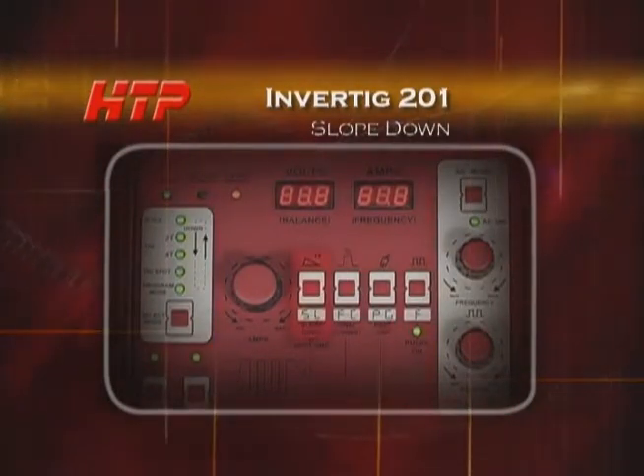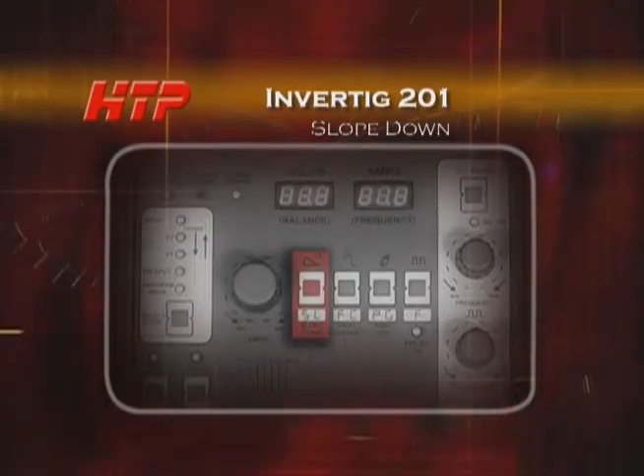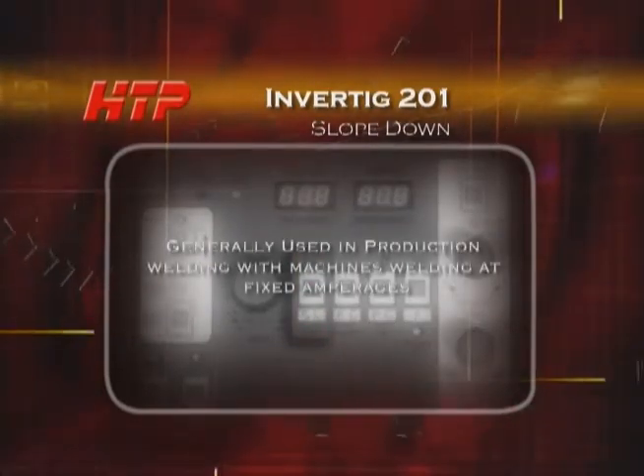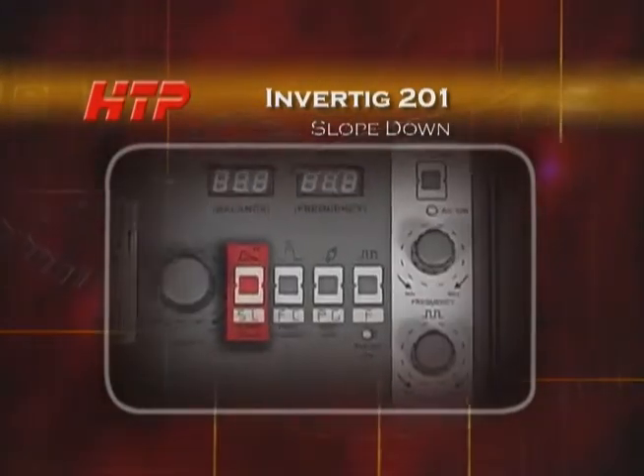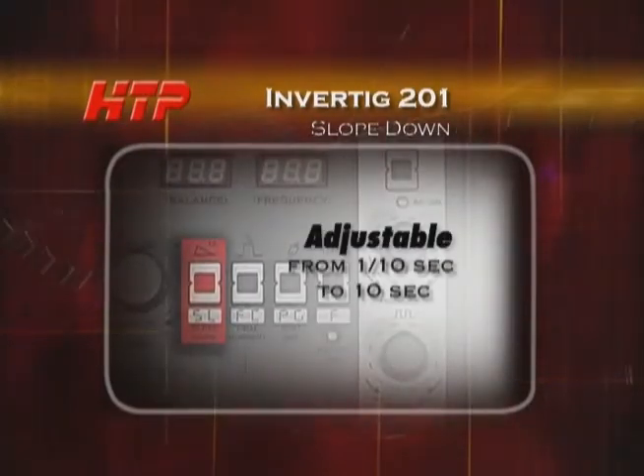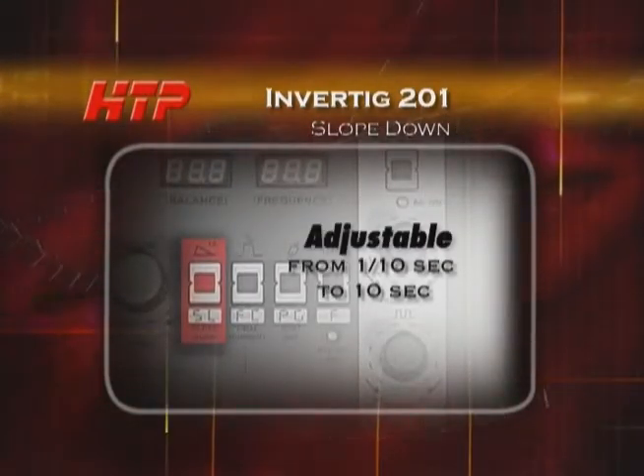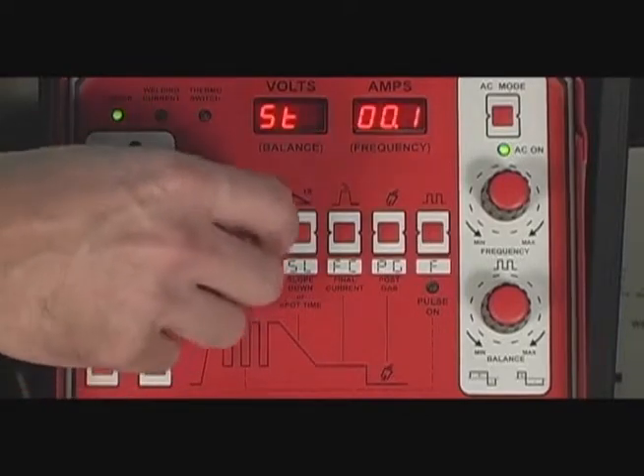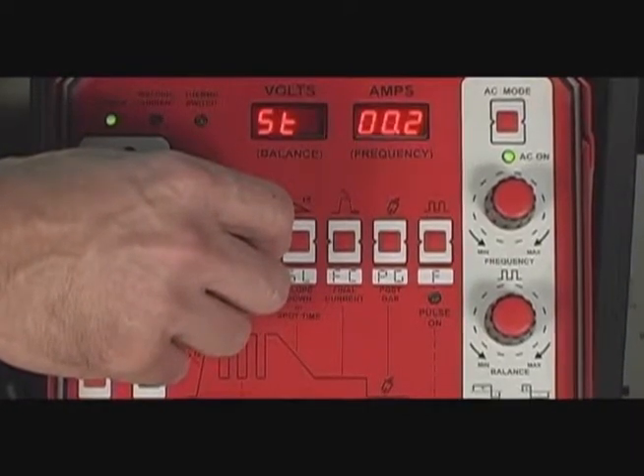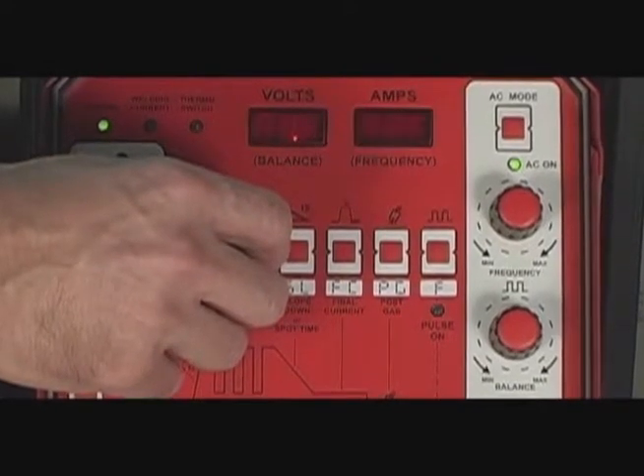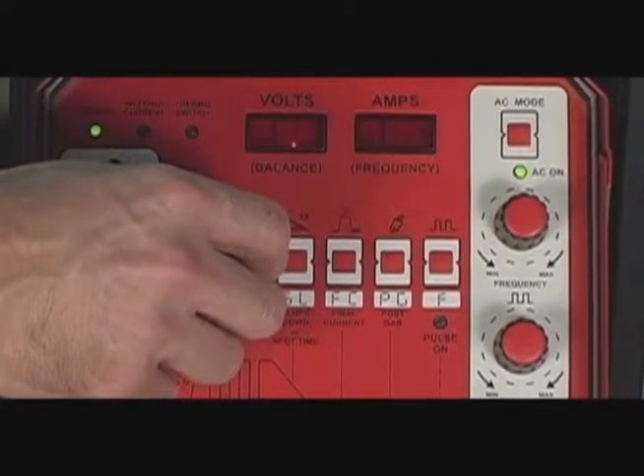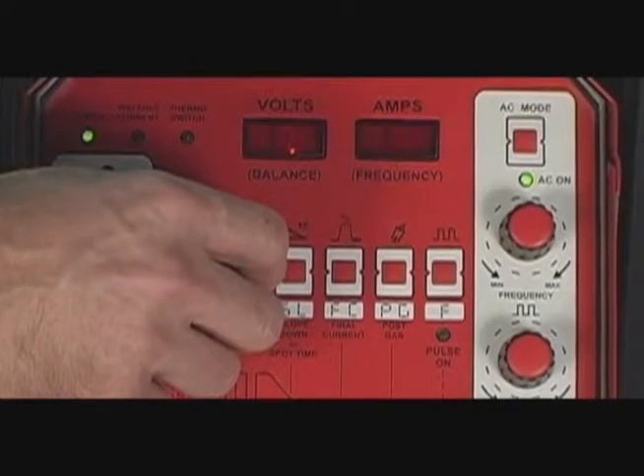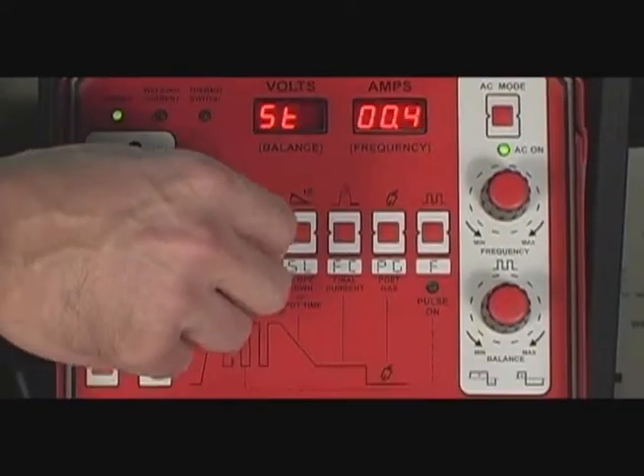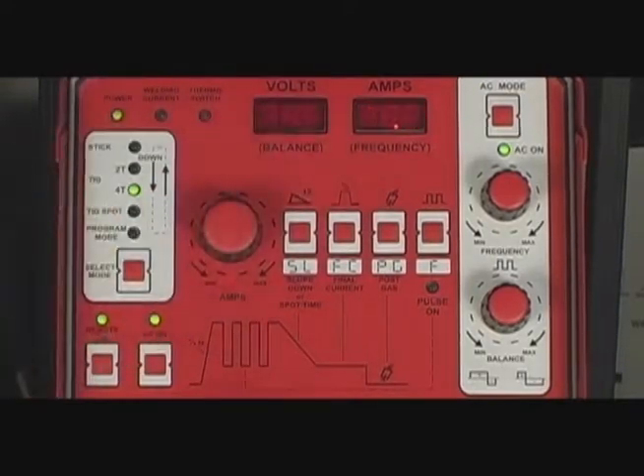Slope down is the amount of time it takes to go from the welding amperage to the final amperage. Generally, slope down is used in production welding with machines that weld at fixed amperages. The slope down time is adjustable from 1/10 of a second to 10 seconds. To set the slope down time, depress and release the slope down button. The volts display will flash SL for slope, and the amps display will flash and display the slope down time in seconds. While both displays are flashing, adjust the amps knob to set the slope down time.